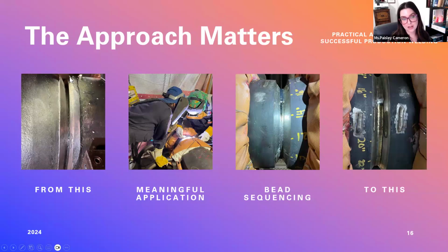But we went through and had not just the weld procedure, which was already qualified, but the specific welders that we flew in from the UK. You can go through and do those really nitty-gritty details where you can take a job or a crack or a repair from something like this, having a meaningful application while working with the welders, talking about the bead sequencing, understanding the appropriate consumables, understanding how the weld is going to be done, monitoring it in nature, and going about how you're going to complete this. Obviously there are those circumferential 360 welds, and it's very tight spots below in particular, because you have all these outlet pigtails shooting out. So it's not the easiest place to get to, but that application can make or break your weld.